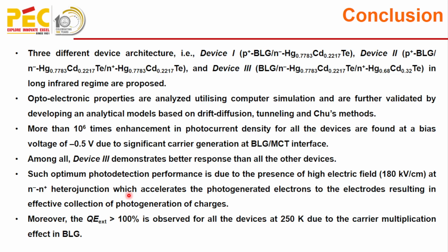And for all the devices, more than 100% efficiency was achieved at 250 Kelvin due to the carrier multiplication effect in the graphene. This is all about my work.